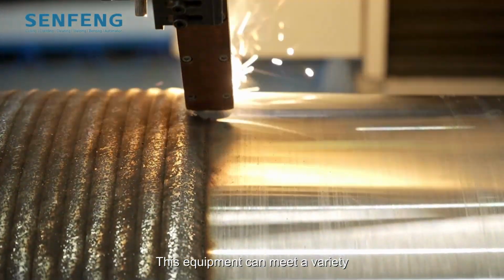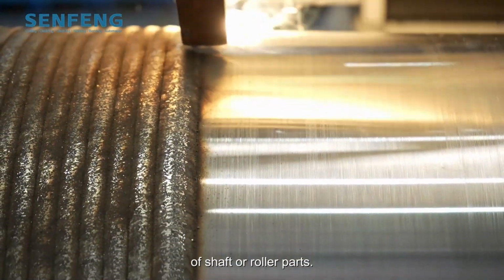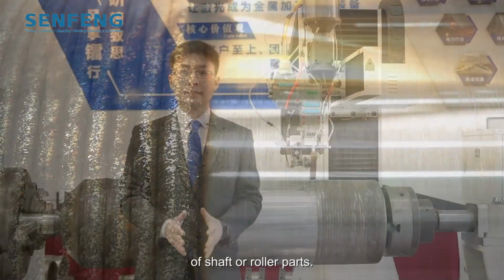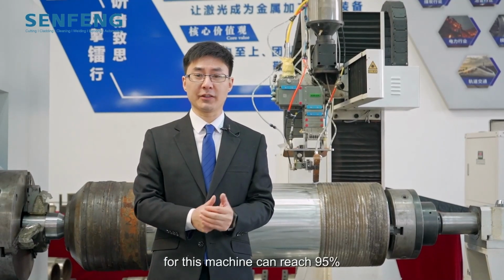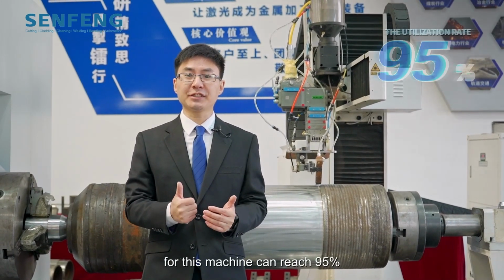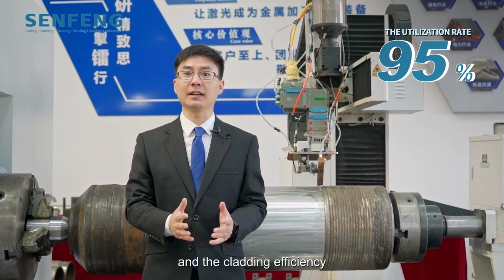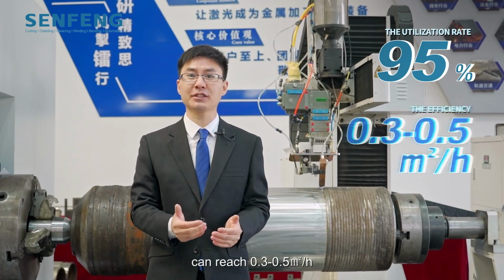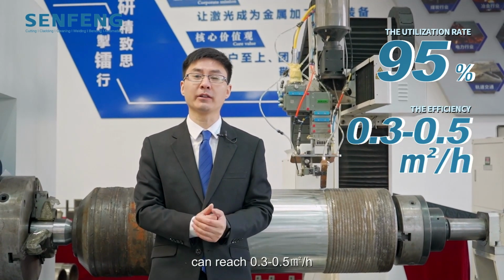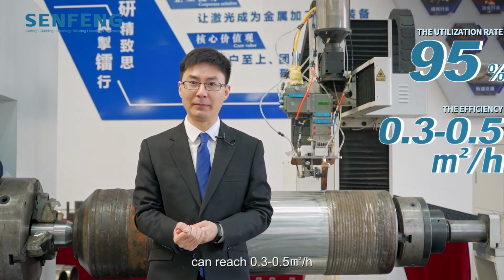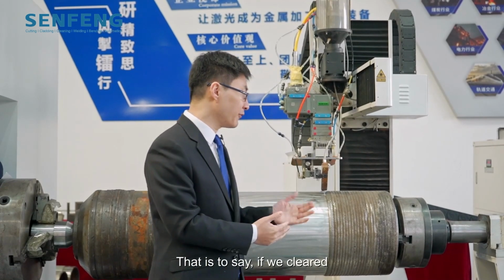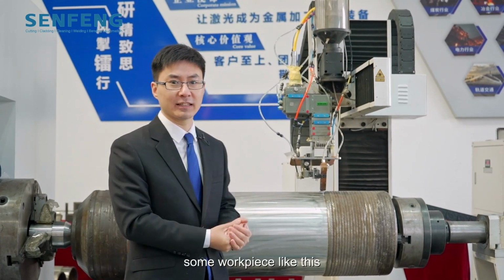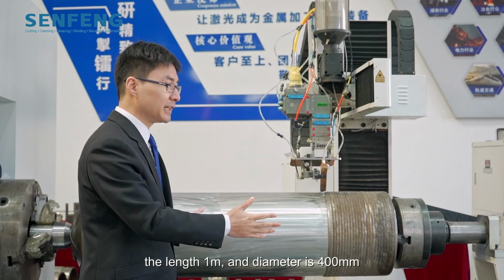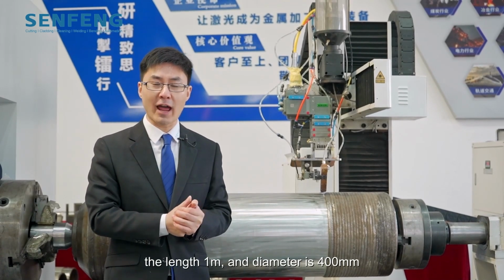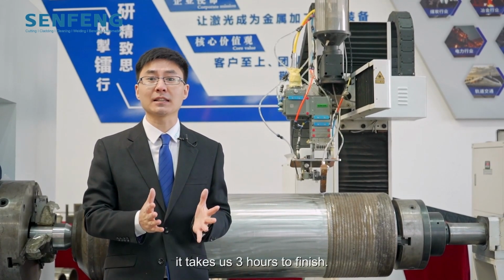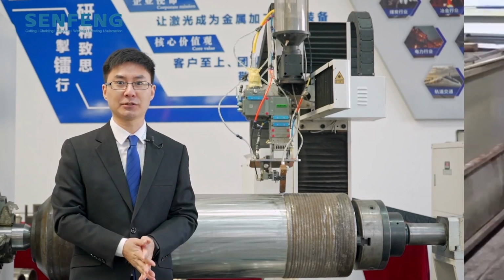This equipment can meet a variety of shaft or roller paths. The using rate of powder for this machine can reach 95%, and the cladding efficiency can reach 0.3 to 0.5 square meter per hour. That is to say, if we clad a workpiece like this, with length 1 meter and diameter 400 mm, it takes us 3 hours to finish.